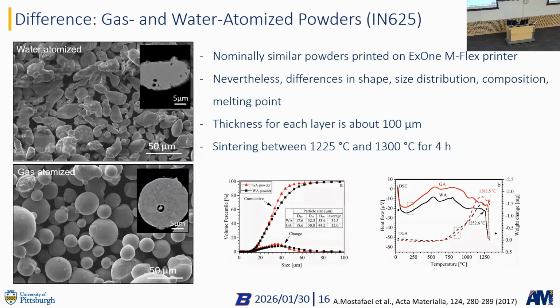So we started with Binder Jet 3D printing now over 10 years ago. And the first project that we had was actually looking at, can we use cheaper powder than gas atomized powder? Gas atomized powder is really nice, spherical, flows super well, but it's very expensive. Water atomized powder, not so good, right? It's not spherical, doesn't flow very well, has contamination and so on. But for industry, it's very interesting because it's much cheaper.